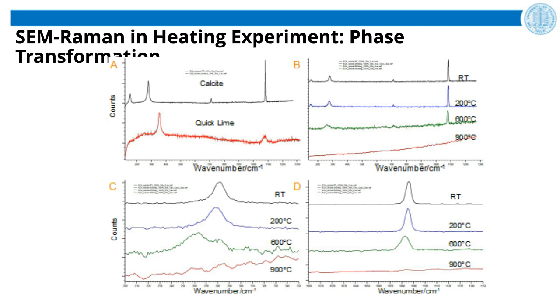Those are visible at 200 centigrade. The 153 peak disappeared at 600. All peaks disappeared at 900 centigrade due to the sample glow, which is a problem for getting a Raman signal. On images C and D, we can see the vicinity of the 280 and 1085 peaks shown with higher zoom.